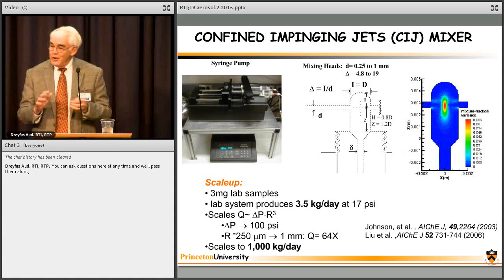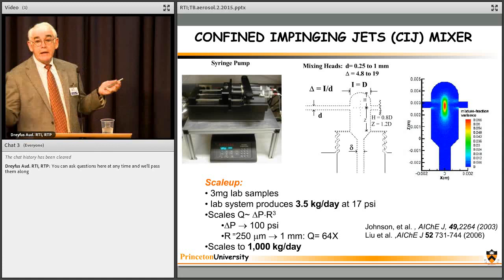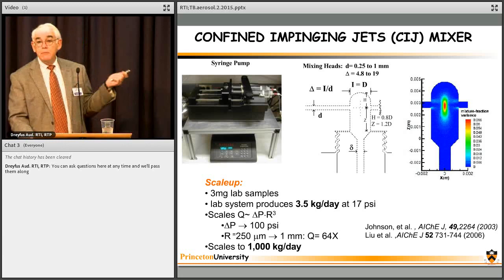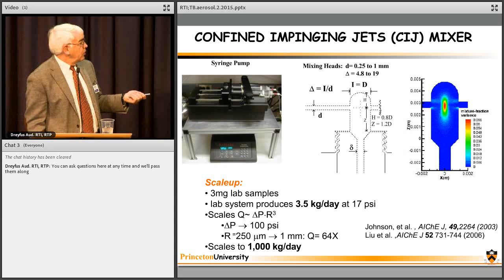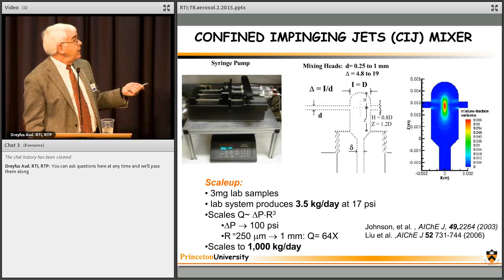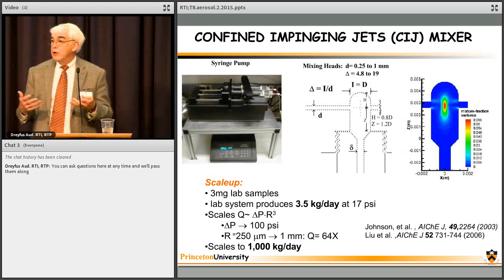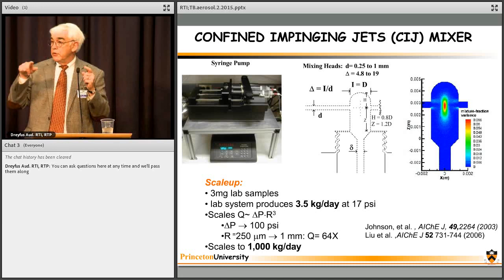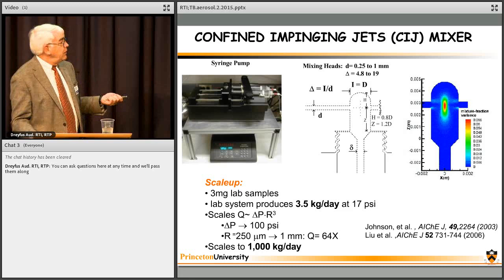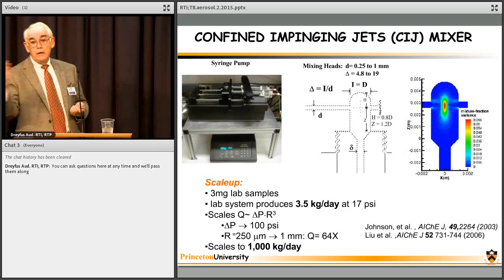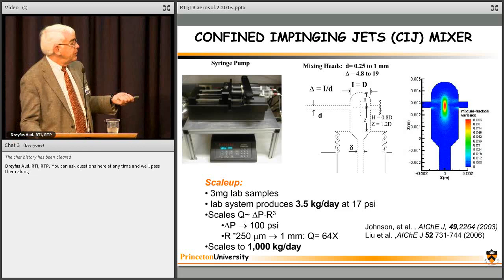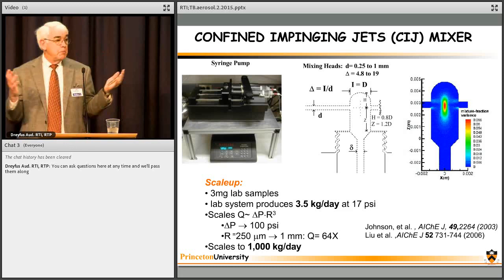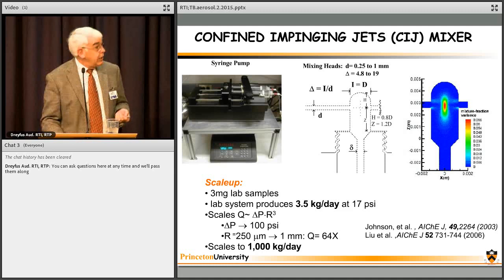It's just the fact that, again, this is scalable from milligrams to thousands of kilograms per day in the same device. And the scale-up is because the flow rate goes as pressure drop to the radius cubed of these orifices. We work at 17 PSI, so these are glass syringes. This is not a 10,000 PSI microfluidics device where you're using tremendous energy to try ripping emulsions apart. All we're trying to do is engineer turbulence so that we get this millisecond and a half diffusion time. And so if you go from 17 to 100 or 1,000 PSI, as BASF operates, that gives you that 10, 100-fold increase in rate. And then you go from 250 micron orifices to a millimeter orifice, a very modest scale up, and you get 64 times. So quickly, in a bank of three of these, BASF can make this 1,000 kilograms per day of 100 nanometer particles. So the scalability and the inexpense of this process is crucial.